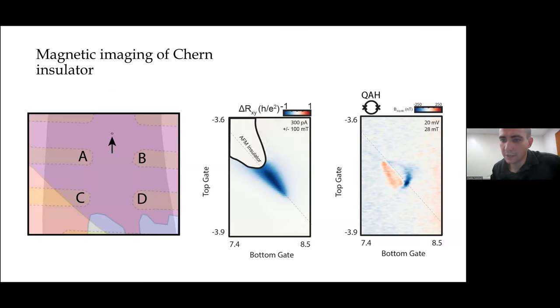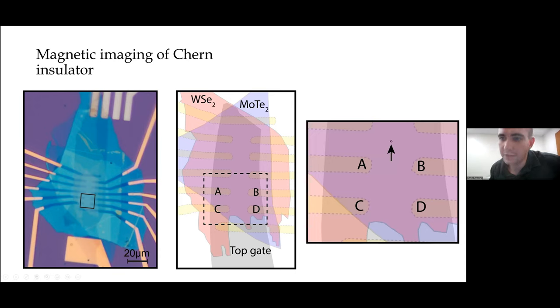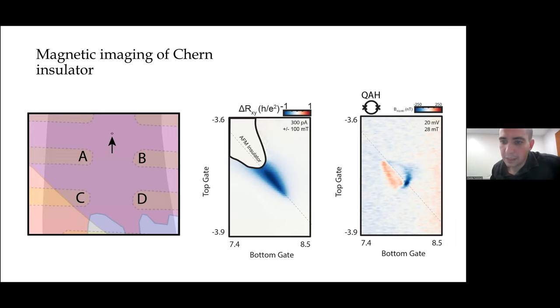So we're going to start by parking the SQUID at one particular point in this device, and then taking a phase diagram with this magnetic contrast mechanism at the same time as we take a phase diagram in the anomalous Hall resistance. So you can see that in the regime where we see a quantized anomalous Hall resistance at relatively small field, we also see the emergence of magnetic order. So we see in this regime a positive derivative of B with respect to bottom gate, and then a negative derivative of B with respect to bottom gate. So what's going on here is a magnet is growing in magnetization and then dropping in magnetization.